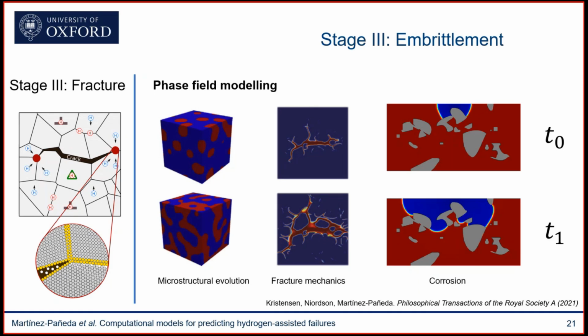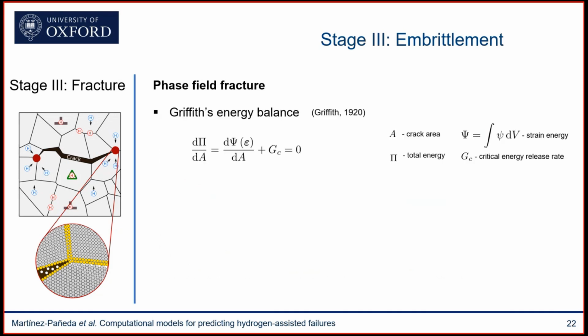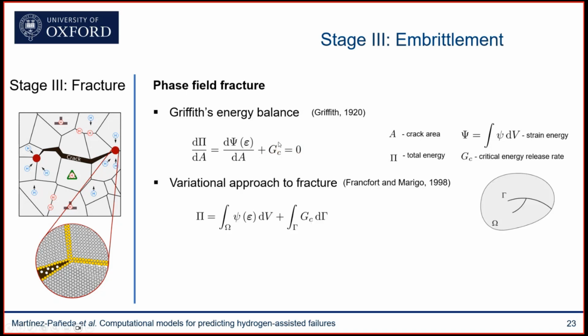And the reason is that phase field provides a computational platform for Griffith's energy method. So it all goes back to Griffith and the foundations of fracture mechanics and the thermodynamics of fracture. As you know, Griffith postulated that a crack will grow whenever the energy stored in the solid is sufficient to overcome a critical quantity, the energy required to create new surfaces, which is the fracture energy or critical energy release rate. And you can postulate this Griffith balance in a variational form. And if you're able to minimize this functional, then you're able to predict the evolution of cracks as an exchange between the energy stored in the material and the fracture energy.